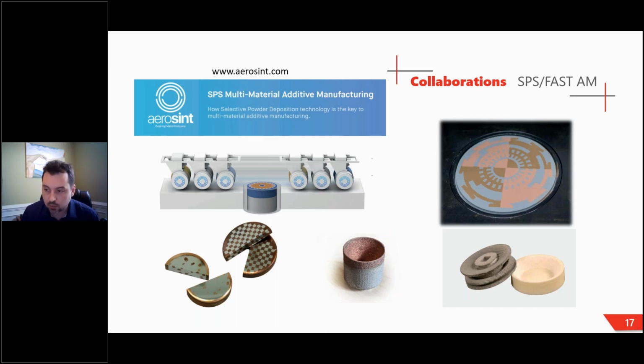And so what this unit does is, you'll notice the 3 different colors on the rollers. As these rollers go back and forth, the cavity is increased in size, and these rollers can deposit each one of those materials very precisely. With a pixel size of about 200 microns by 80 microns, we can deposit very specifically powder A, powder B, and powder C. Now, in some cases, all those powders might be sintering together to make a composite component, which might have built-in heat sinks, built-in channels, things of that nature, different materials bonded to each other.